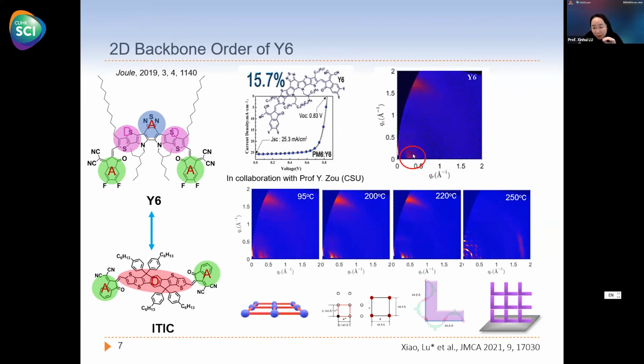But we see two broad peaks, which indicates that there might also be some additional structural order in the in-plane direction. So to understand the backbone packing in the in-plane direction, we heat the sample to promote crystallization. We can see that when we increase the temperature, the Bragg peaks become more and more clear, and at 250